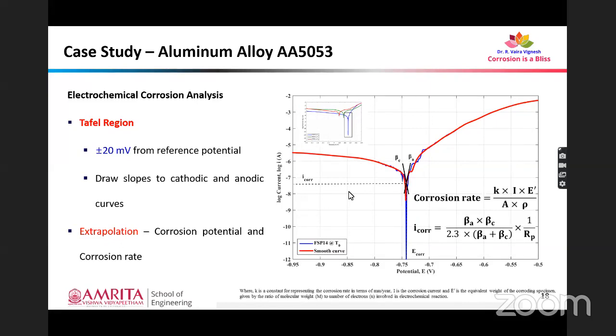So from this Icorr value, we can identify the corrosion rate of the specimens using the equation given over here, which is: corrosion rate is equal to K into I E' by A into rho, where K is a constant representing the corrosion rate in terms of mm per year, I is the corrosion current, E dash is the equivalent weight of the corroding specimen, given by the ratio of molecular weight to the number of electrons involved in the chemical reaction.